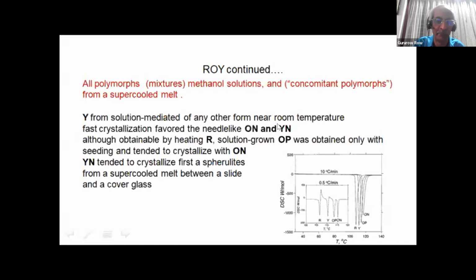We can separate them under the microscope looking at the color. And although obtainable by heating R, the orange prisms can be obtained only with seeding with the orange crystals. And they tended to crystallize with orange needles and yellow needles. So you see that one is convertible to the other. They all come together, but because of the color variations and the polymorphic modifications, the morphology that is associated with it helps us in separating these forms. Very interesting compound, very important compound in the sense of trying to see and understand what is polymorphism.